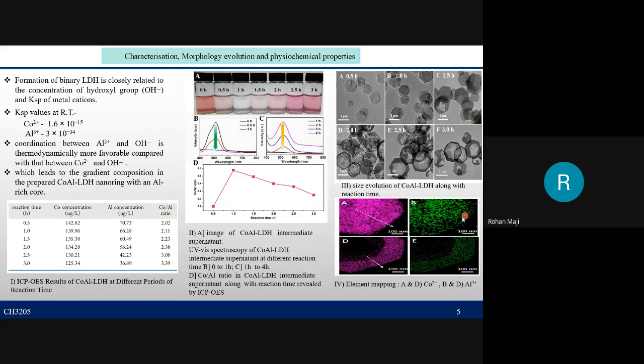In the element mapping through EDS, that is energy dispersive spectroscopy, the increased cobalt to aluminum ratio from the center to the edge reveals the gradient distribution of cobalt 2+ and aluminum 3+ in the nanosheet, where aluminum 3+ enriches the core and cobalt 2+ enriches the edge.